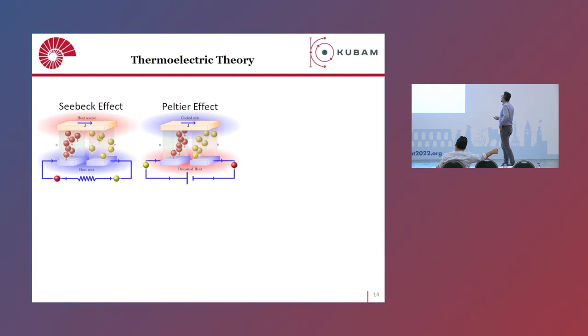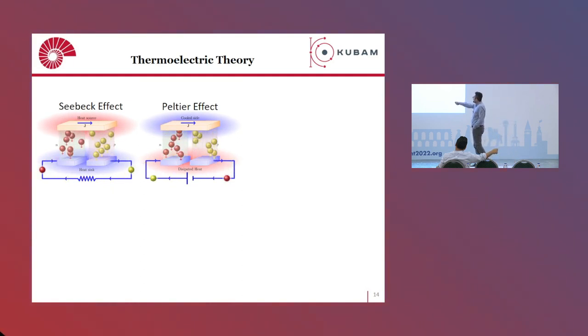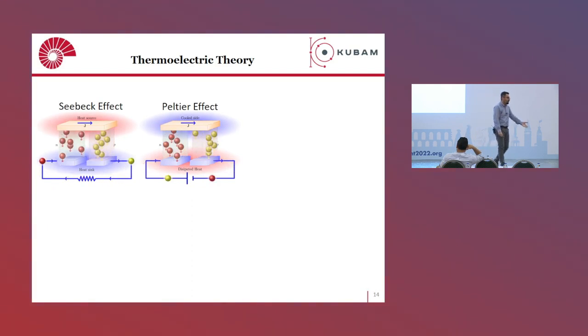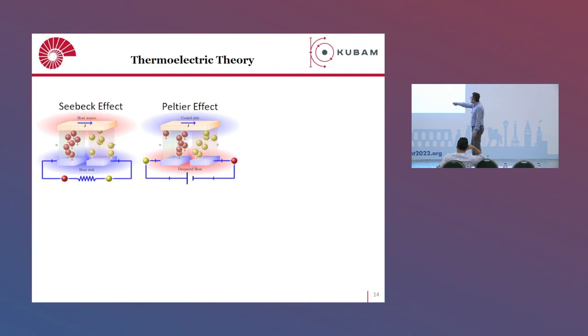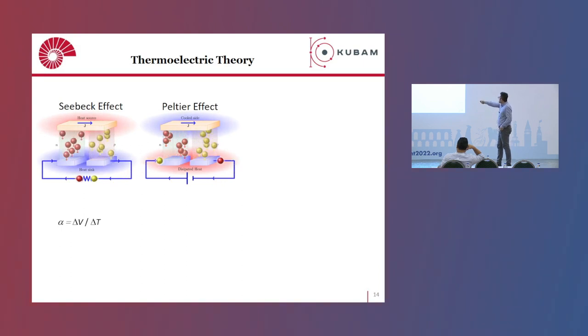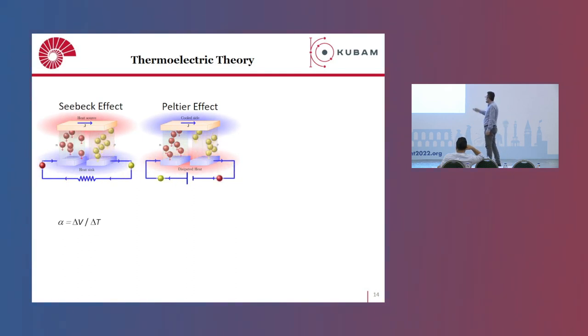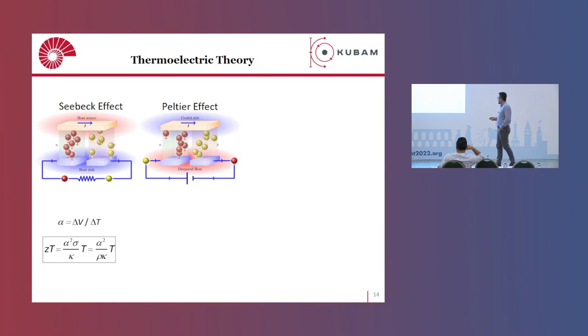So here is the thermoelectric theory. These are based on the Seebeck effect for power generation and the Peltier effect for cooling. Here we have n-type and p-type semiconductors. If we create such a circuit and apply a thermal gradient, this produces voltage, because we force the charge carriers to move from the hot side to the cold side, similar to gas molecules, and this creates a potential difference. The potential difference you create per temperature gradient is called the Seebeck coefficient. For the same circuit, instead of applying a temperature gradient, if you apply current, then you create a temperature gradient, which means you can use it as a Peltier cooler. This part will be cooled, this part will be heated, and you can dissipate this heat with some methods.